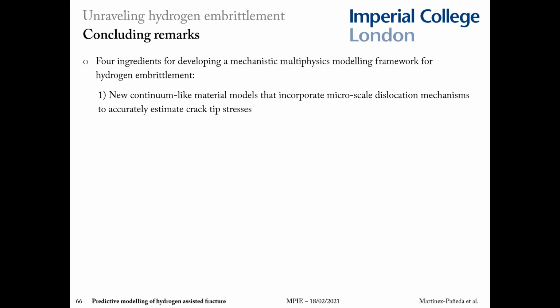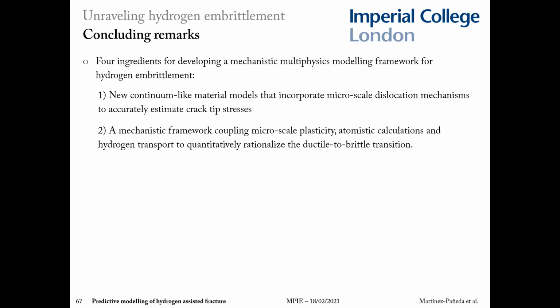So let me just finish by providing some concluding remarks. I would just say that developing models for predicting hydrogen embrittlement is indeed challenging, but I think that this elusive goal can be tackled if one considers first enriched continuum models such as strain gradient plasticity that can calculate precisely crack tip stresses at a few microns ahead of the crack tip, which is the critical distance for hydrogen-assisted fracture.